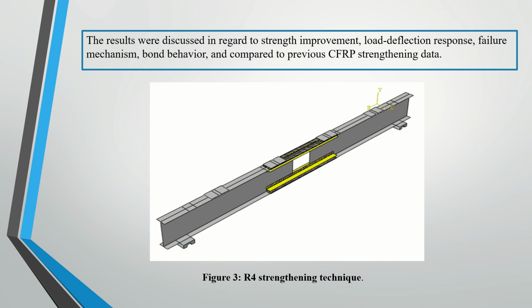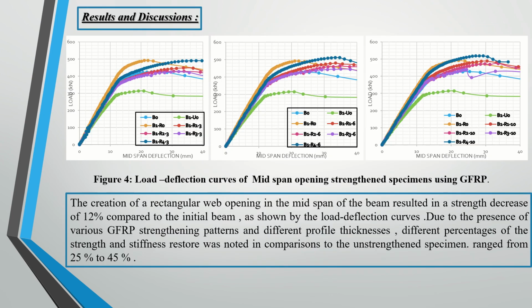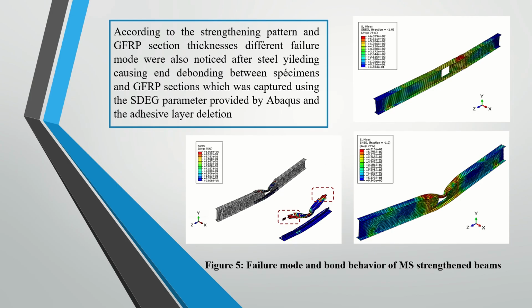The results were discussed in regards to strength improvement, load deflection response, failure mechanism, and bond behavior, and compared to the previous CFRP strengthening data. The creation of a rectangular web opening in the midspan of the beam resulted in a strength decrease of 12% compared to the initial beam. Due to the presence of various GFRP strengthening patterns and different profile thicknesses, different percentages of strength and stiffness restoration were noted, ranging from 25 to 45%.